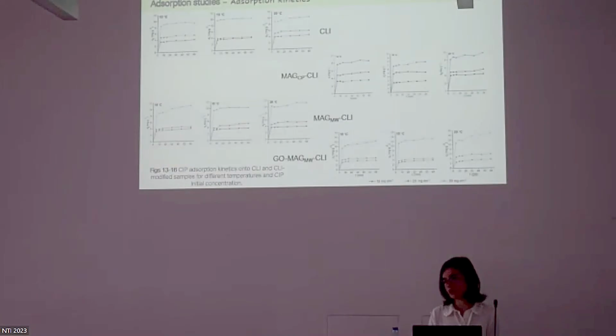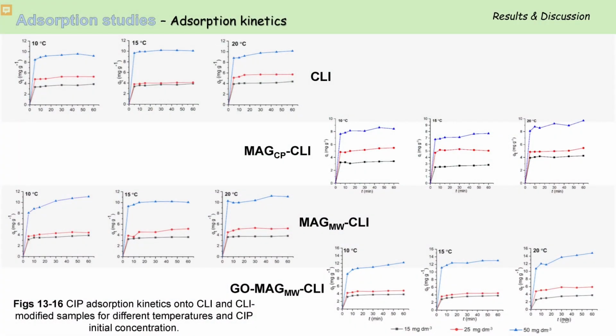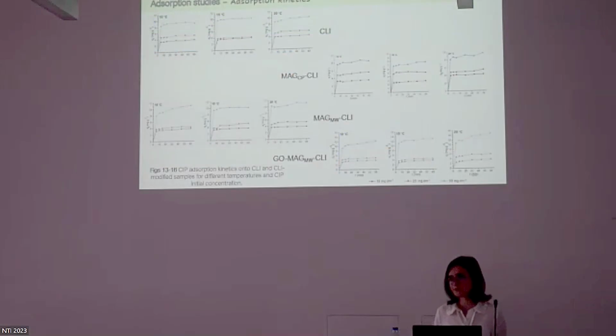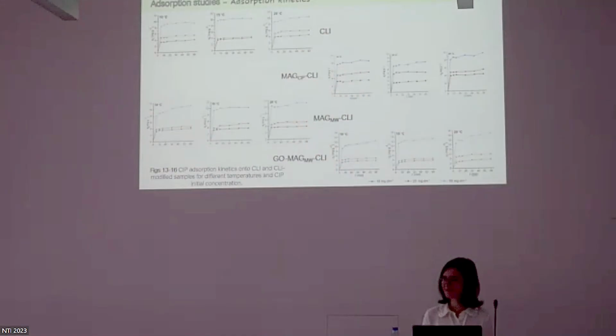Okay, thank you. And the second question: could you compare the adsorption capacity of ciprofloxacin removal using modified zeolite for both methods? There is no significant difference, I would say. As we can see here, both magnetic clinoptilolites have practically the same adsorption capacity for all the investigated temperatures and initial concentrations. So it is only the surface morphology and what species you obtain, and the species affect not the adsorption capacity, but just the magnetic properties.